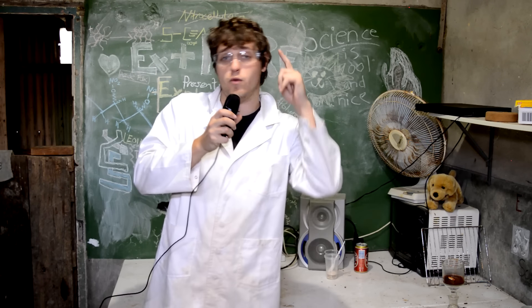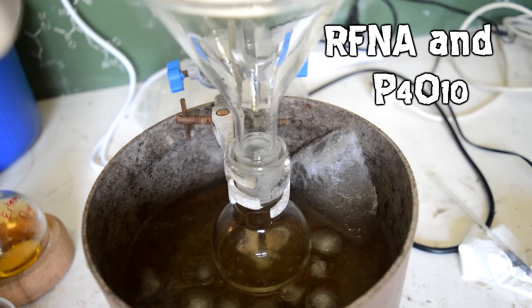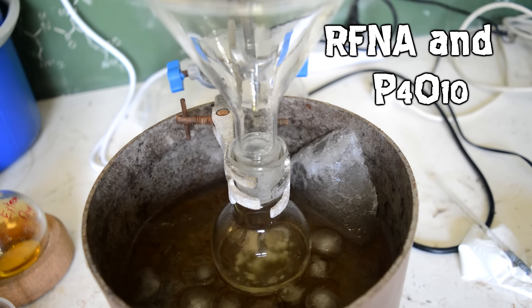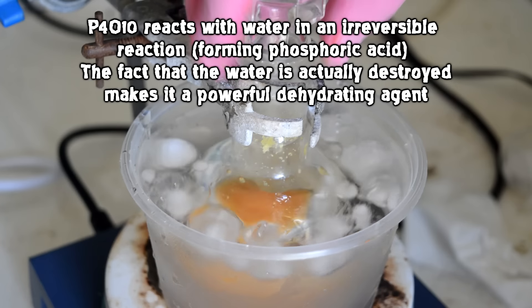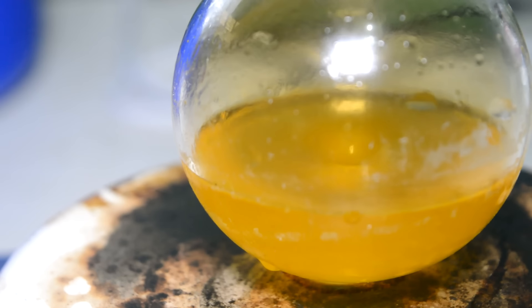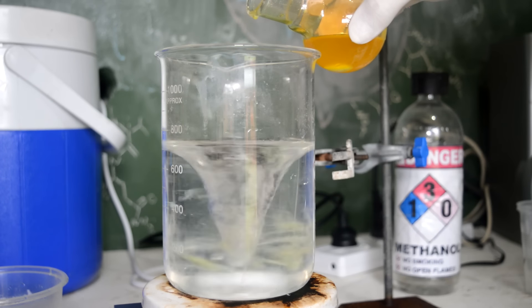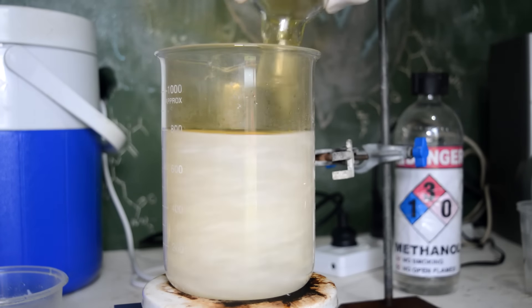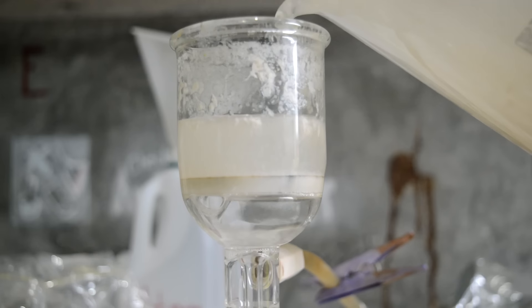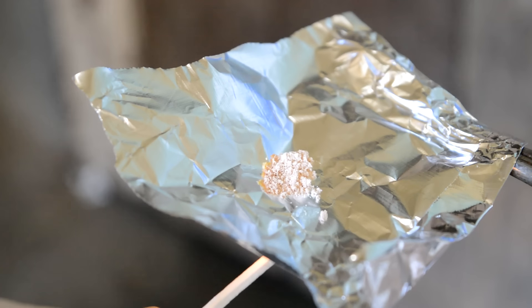We need a different dehydrating agent that won't precipitate our mixture — that is phosphorus pentoxide. We're stepping it up a notch. This is fine as long as our cooling bath is up to the task, because it gets a little wild. We slowly add our ground polyvinyl alcohol. This reaction runs a lot better — we end up with a basically clear solution, no lumps of polymer precipitated out. Even though it's all polymer, it's actually dissolved into the nitration bath, allowing it to nitrate properly. This gives a nice uniform powder when we precipitate it out into water.